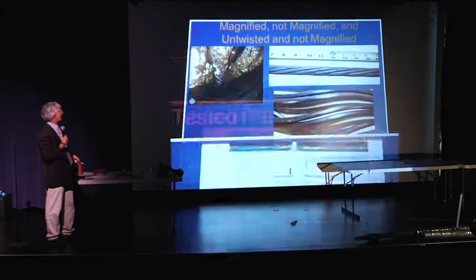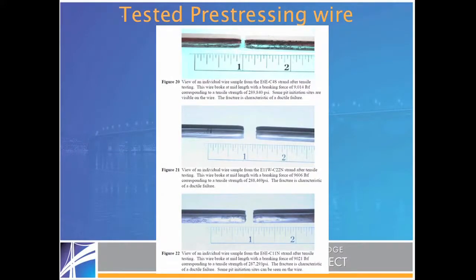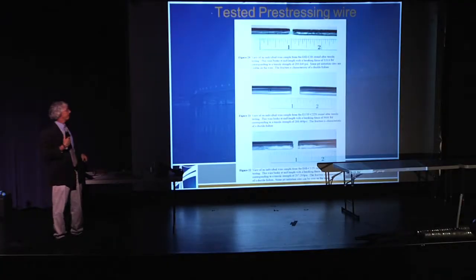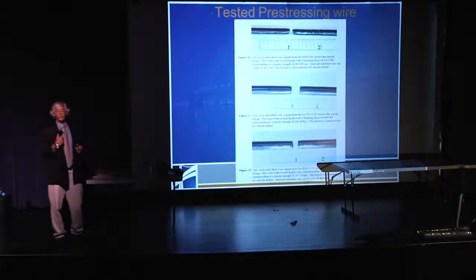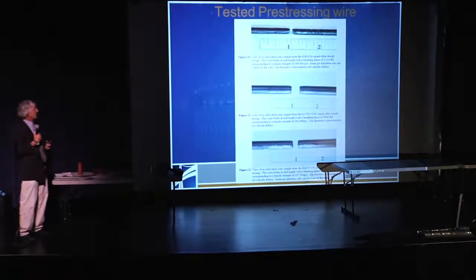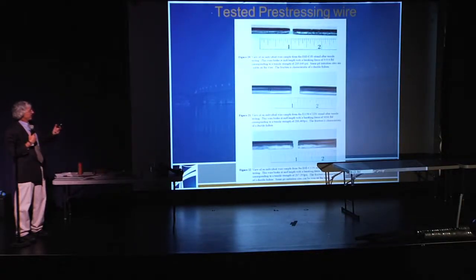Next slide. Then we took some of those wires, because when we saw some of this, when we see pitting, that is a change of surface, we get concerned about stress concentrations. And in some cases, we said, get it out. Take it out, putting in a new tendon, okay? But in some cases, we actually tested some of the wires. And here's a sample out of the report where we actually see the wires, after testing in tension. And the shapes are very important because they tell us we still have a ductile system. That means the stress concentrations are not changing the type of ductile final product we have after a test. Next slide.